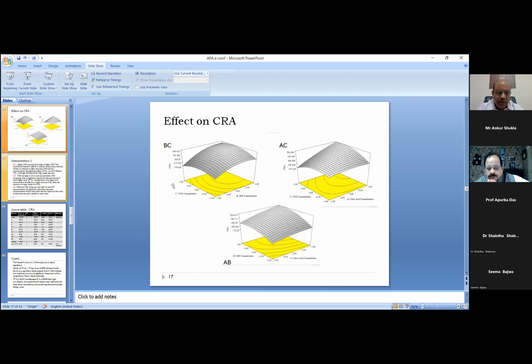With this Box-Behnken design of experiments, this was the effect on CRA. If we see the graph here, the first one is an interactive effect between B and C, that is the concentration of sodium hypophosphite and the concentration of TiO2. Here we find that as the SHP concentration increases, there is also an increase in the crease recovery angle. This clearly states that with a higher concentration of the catalyst, the phosphorus-based catalyst, there is an increase in the crease recovery angle. And this is what we in fact wanted.